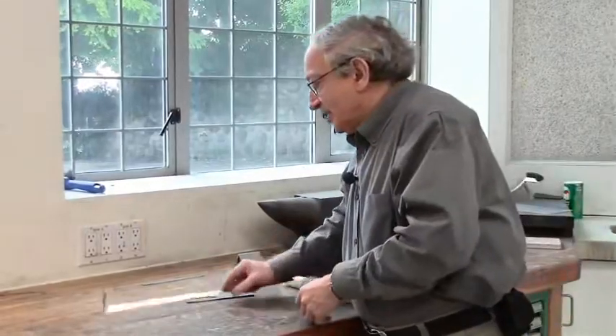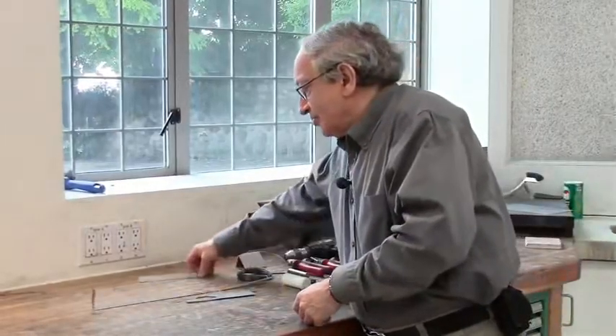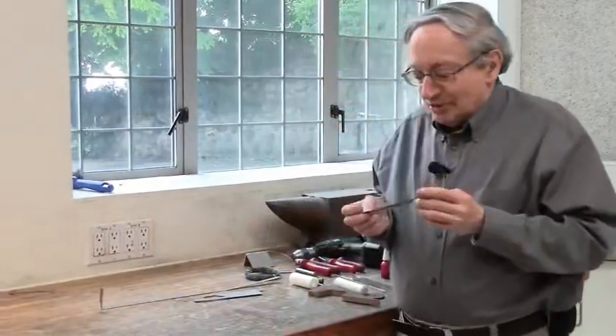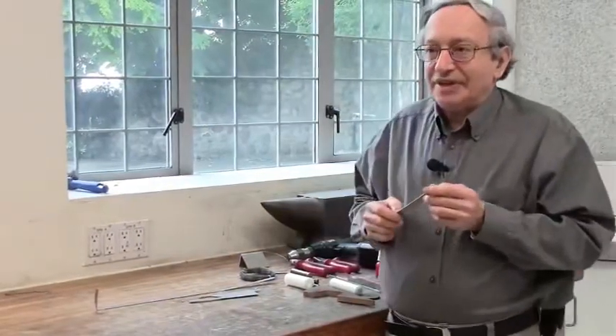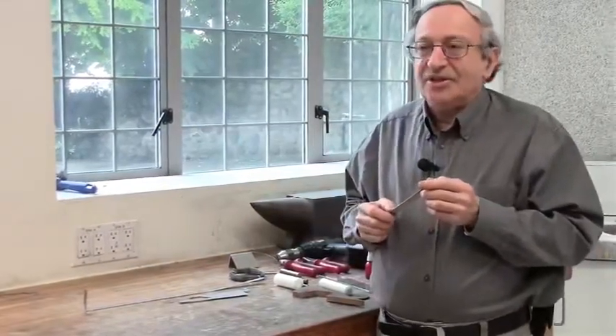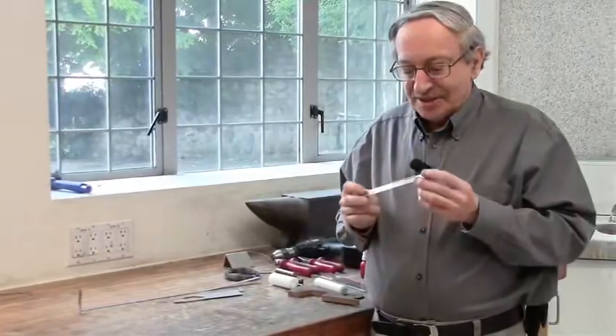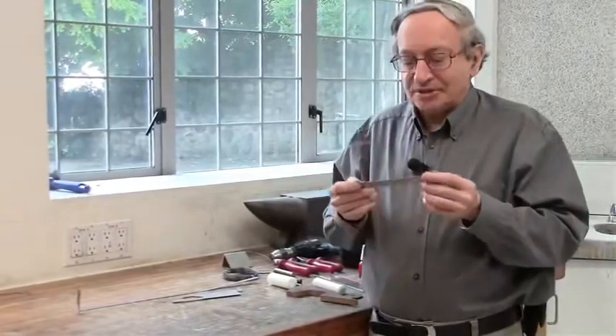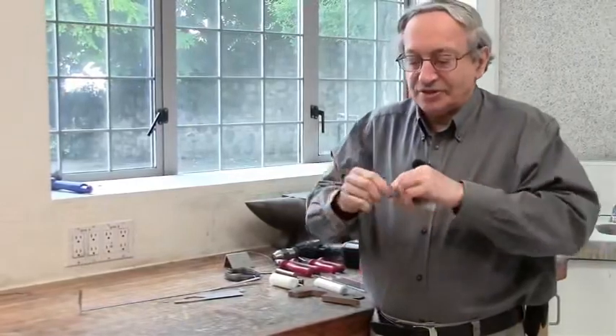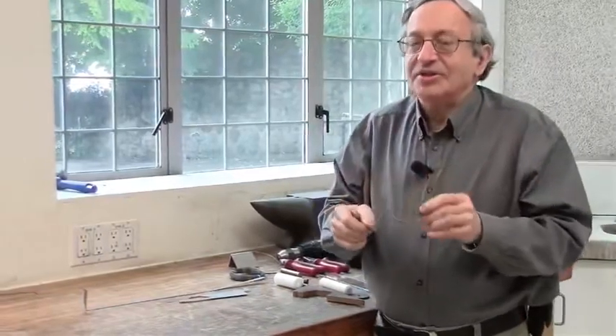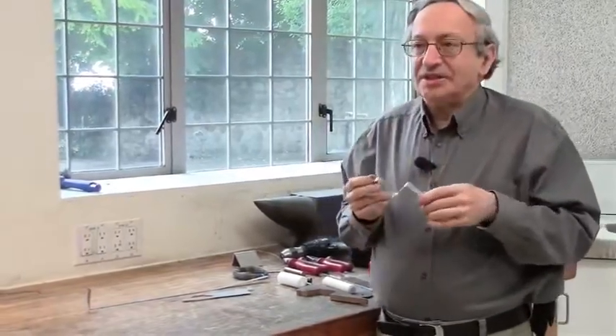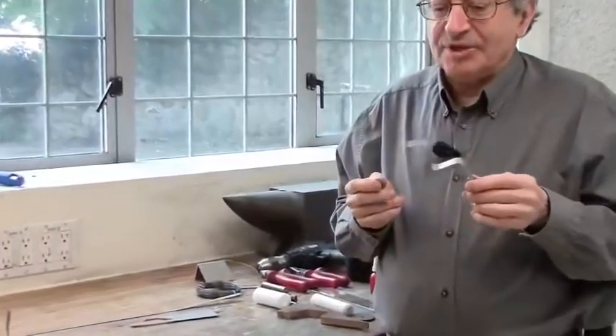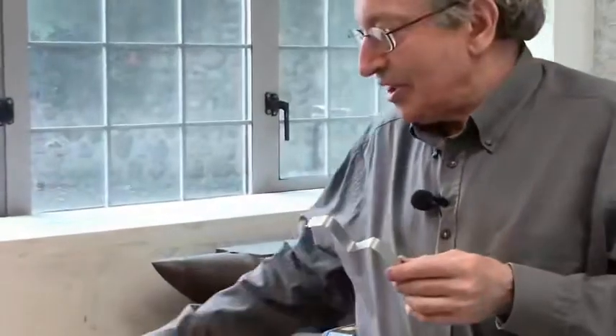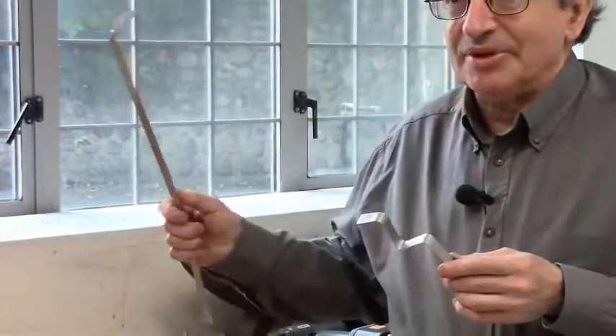Now, the other type of stainless spring temper I would store is something called a 17-7 stainless steel, and this is a type which comes annealed, it's very, very soft, you can see, but if you do a heat treating cycle in the oven, it becomes very hard and very springy, much harder, much springier than the spring temper. That's probably the strongest and springiest stainless steel there is.